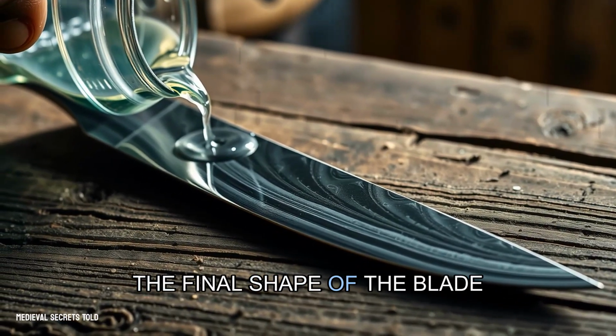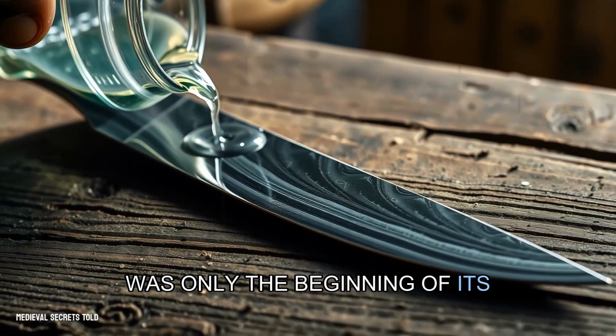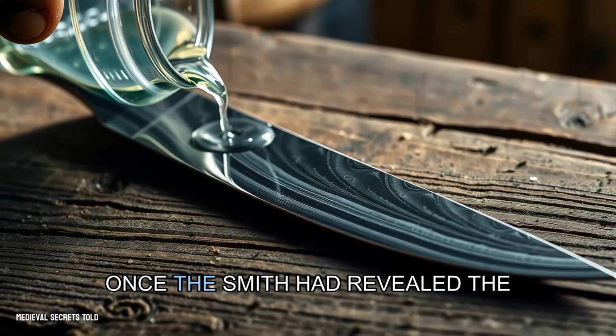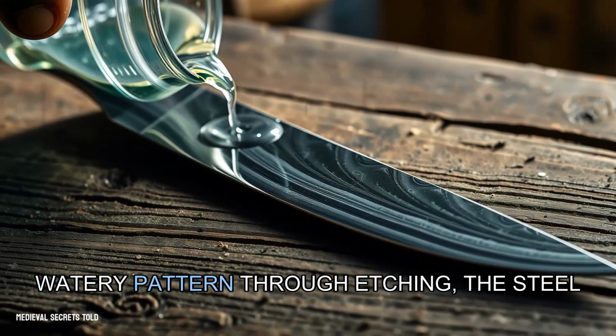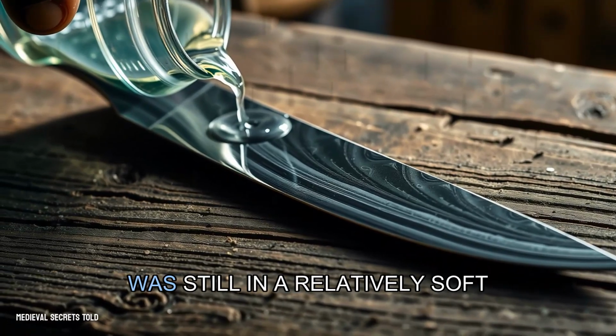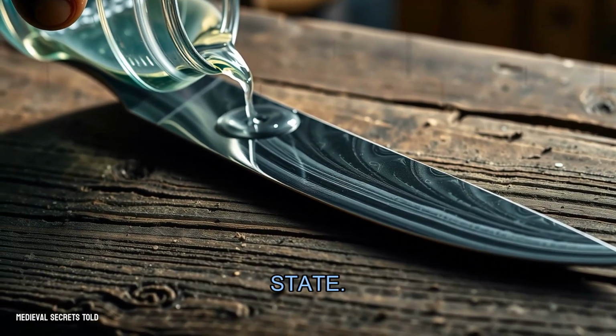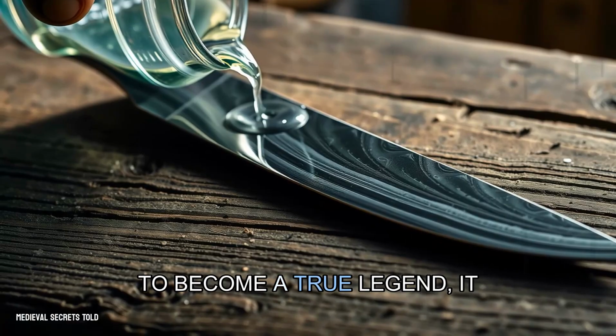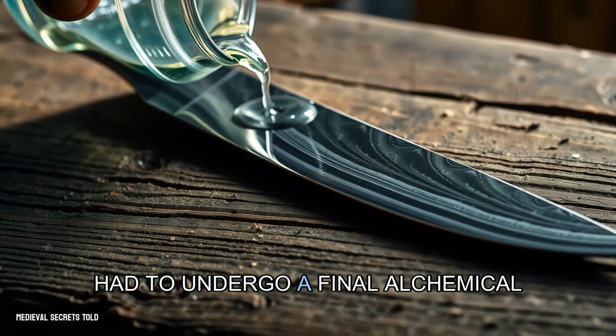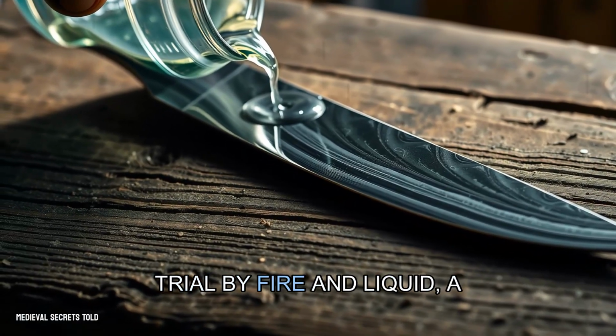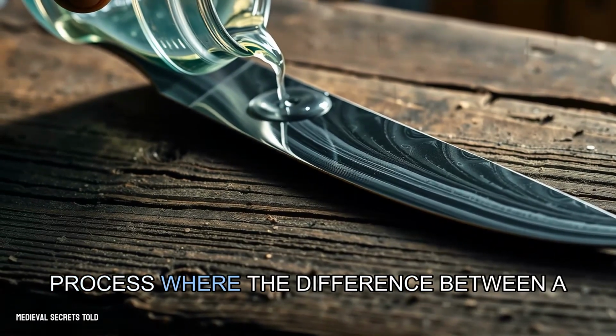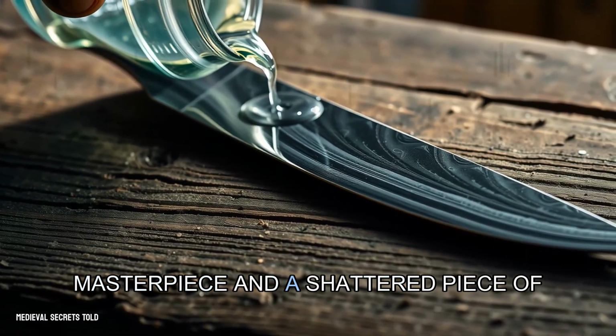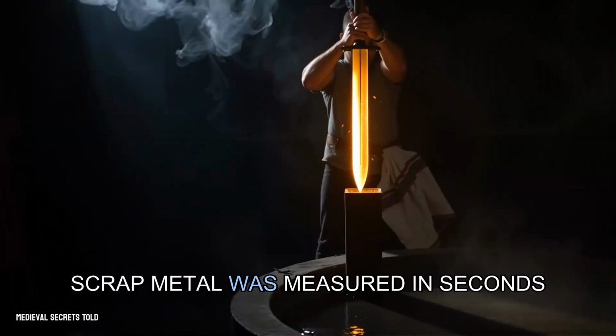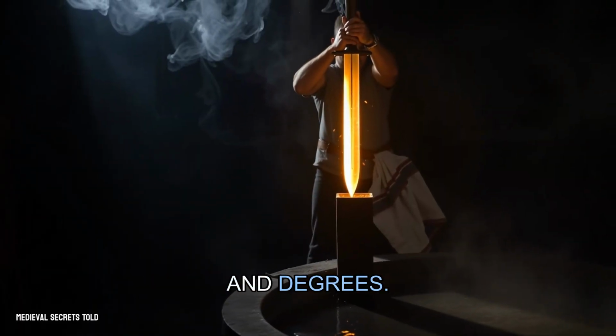The final shape of the blade was only the beginning of its transformation. Once the smith had revealed the watery pattern through etching, the steel was still in a relatively soft state. To become a true legend, it had to undergo a final alchemical trial by fire and liquid, a process where the difference between a masterpiece and a shattered piece of scrap metal was measured in seconds and degrees.